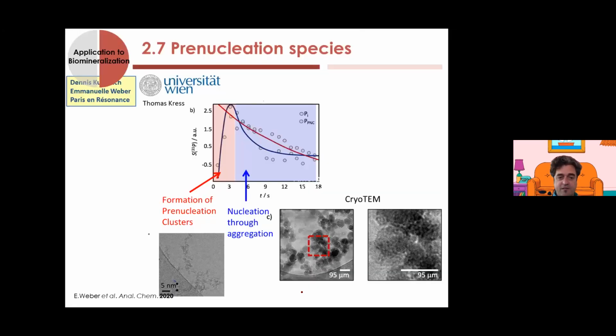I have one very general question and then a more particular one. The particular one is related to your last slides about the nucleation and pre-nucleation of the calcium phosphates. It's very interesting that you could follow a very fast process like that. Do you think that, for example, going to homogeneous precipitation instead of mixing, trying to have phosphate esters that decompose and then create a slower supersaturation, can give you more information about this, or will the regime change? What are your comments on this? Because I found it very nice.